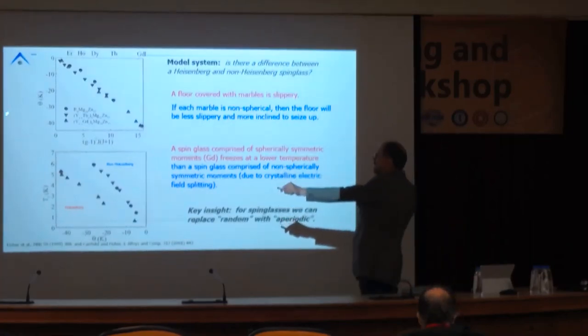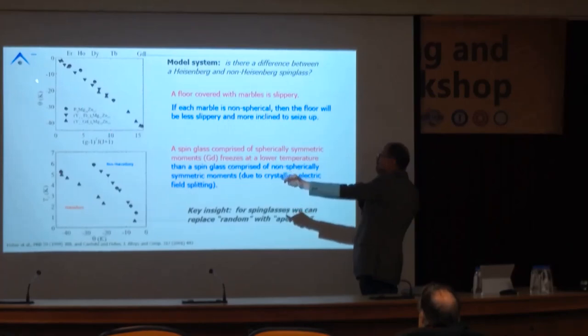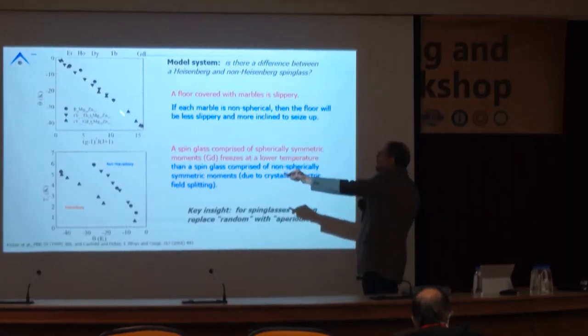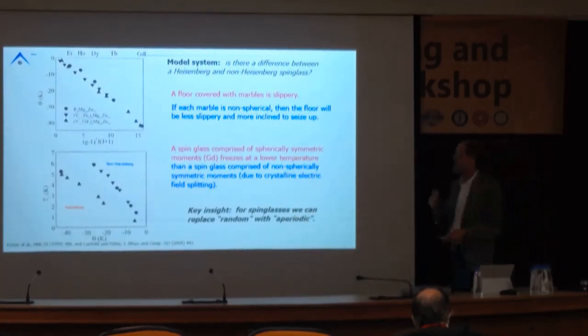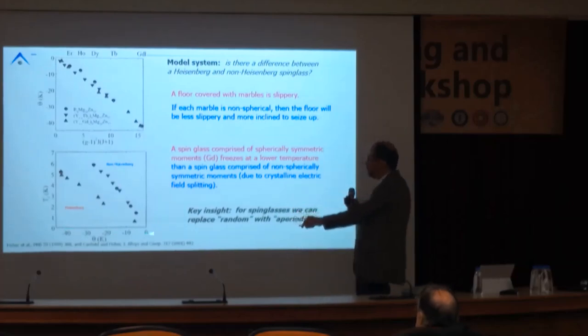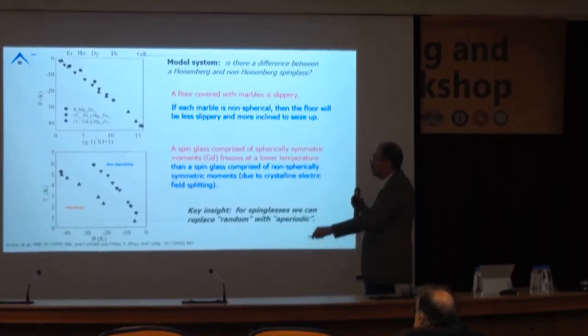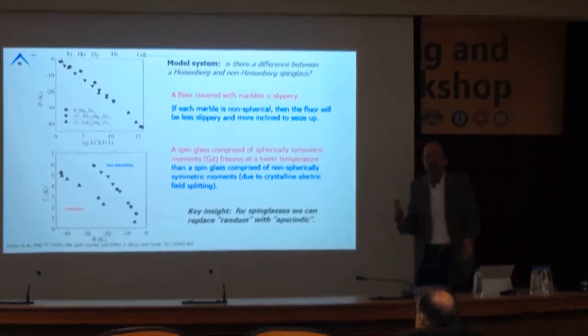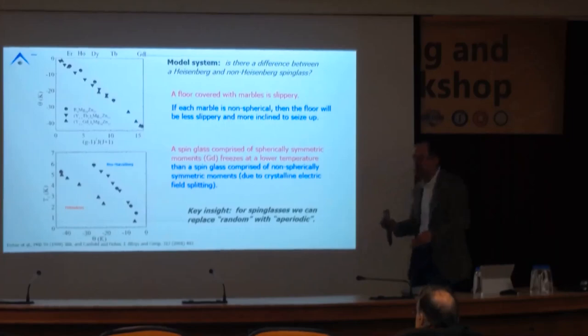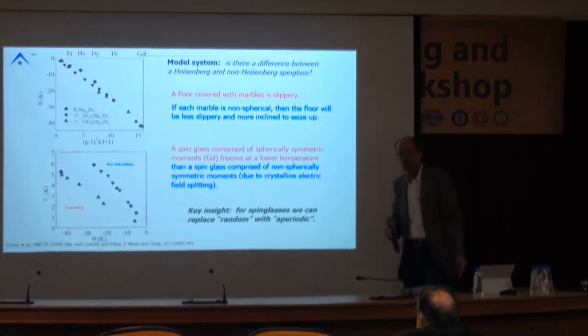We can look at the paramagnetic theta versus the de Gennes factor for all of these, for the pure rare earth magnesium zincs, as well as the yttrium terbium and yttrium gadolinium mixtures, and they all scale almost in a textbook fashion. Okay? On the other hand, if we take the freezing temperature versus the theta, two experimentally measured parameters, high temperature and low temperature, this breaks into two manifolds. We have a Heisenberg manifold, all the gadolinium, and a non-Heisenberg one. Okay? And what we can see is for the same theta, a non-Heisenberg spin glass freezes at about twice the temperature. We can back that out into understanding that if the floor was covered with marbles that are perfect spheres, it would be slippery. If we squared those marbles up, it would be less slippery, it would freeze more readily.